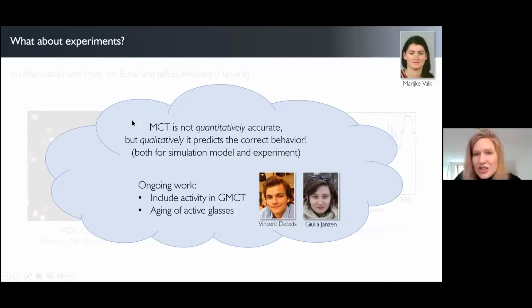already a very encouraging result that the crudest version of this theory, again, developed in the early 80s for normal glass forming liquids that are not active and not alive, can do a pretty good job to already qualitatively predict the behavior seen both in these active cell simulation models, where we saw this non-monotonic behavior, and in the real experiments, where we see a monotonic increase in relaxation time.